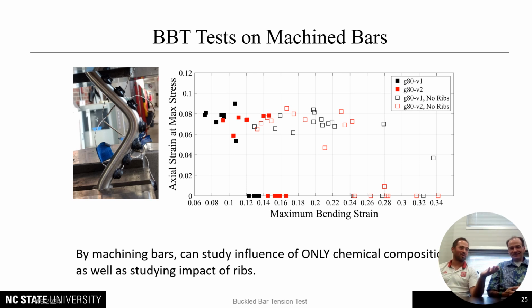So we sent this, an actual rebar, I think it was to the machine shop at NC State. Exactly. We just had to mill the ribs right off the bar and see, well, what is the critical bending strain with these bars with no ribs at all? And we saw that, so this was, again, the black, same bars that we ran in the column test with the lower critical bending strain. The red was the higher radius, so lower strain concentration.